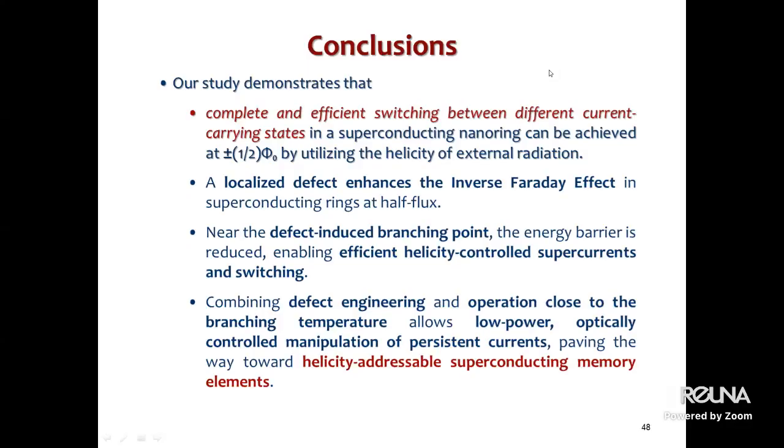No. Originally, we investigated the switching effect in a clean sample. Then a question appeared, because defects are unavoidable in the system, especially in such a small system. So we started to investigate the influence of defects, and then a bistable system appeared. In one situation, the effect is totally destroyed, the switching, not the current, because two effects were interesting to us. One is switching for the quantum computer, and another one is simply linear response. Linear response is perfectly working, but switching basically was killed.